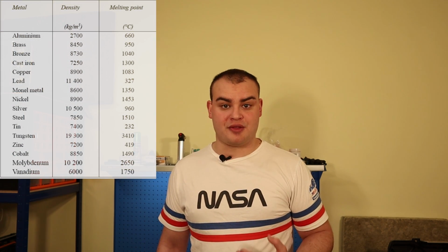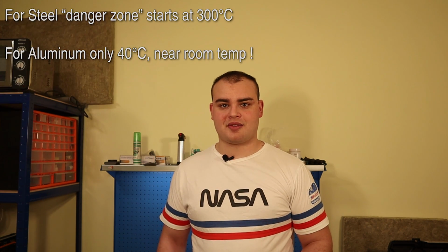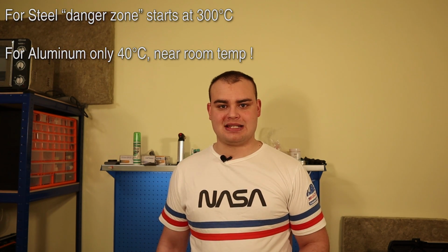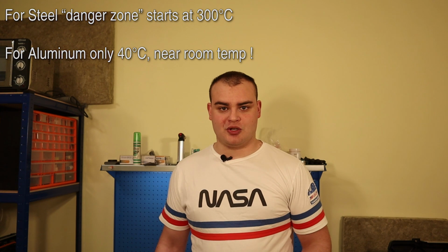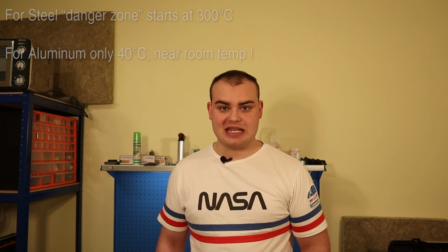Now, these phenomena are essentially caused by thermal agitation of atoms and are therefore of a significant magnitude only when the operating temperature of the component is high enough compared to the metal's melting temperature. In detail, if the operating temperature is less than 1/3 of the absolute melting temperature of the alloy, the material creeping is extremely slow and in common designing practice is totally neglected. For steel, the threshold temperature is about 300 degrees Celsius, so at room temperature and in typical use, which is always under 50 degrees C, creep and relaxation are practically non-existent.